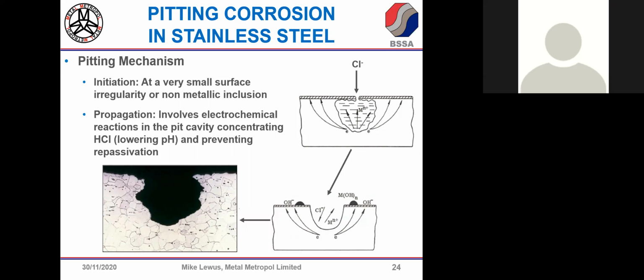one of the Achilles heels is chloride, the presence of chloride. It's a very mobile, small ion that destabilizes the bonding in oxides. So it causes that nice protective chromium oxide layer to break down. And as soon as it breaks down, the electrochemistry that's operative once that protective layer is broken down actually produces hydrochloric acid in the pit that occurs.